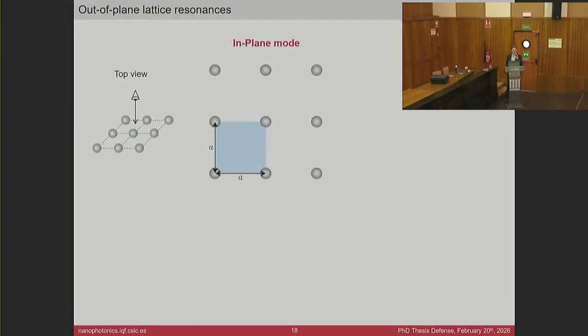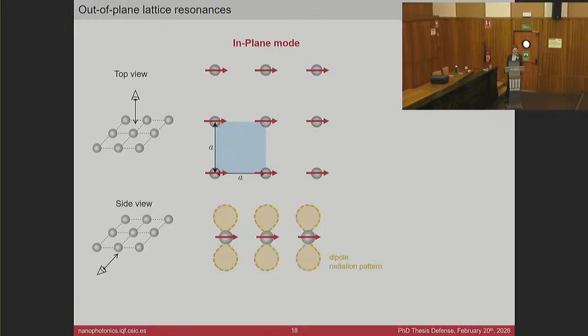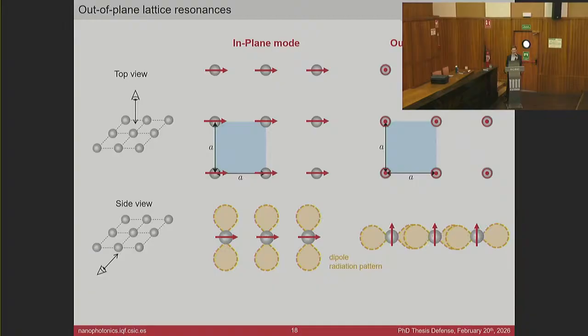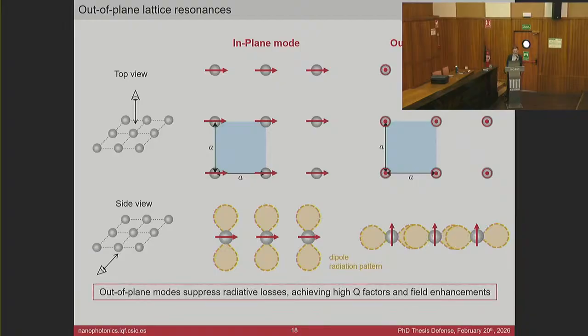Let's just understand first why these resonances are so relevant. So far we have seen in-plane modes, and if we plot this from a side view, we can see from its radiation pattern that this configuration favors the radiation of energy out of the array. However, if we have now our dipoles perpendicular to the plane of the array, we have a configuration in which these radiative losses are inhibited. They are highly suppressed, giving rise to large quality factors and also large field enhancements.